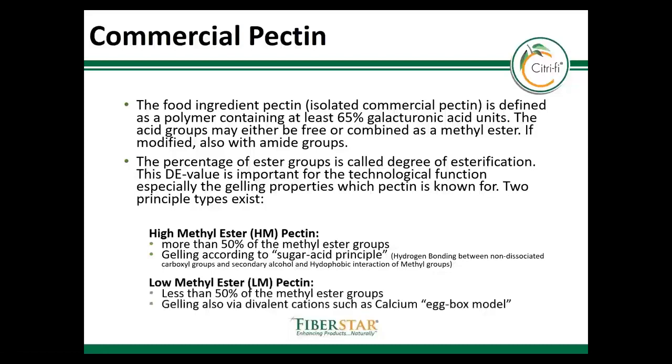LM pectin, on the other side, has less than 50% methyl ester groups. Instead of hydrophobic binding, the polymers can form gels via bivalent cations such as calcium. The gelation works also under low sugar conditions.